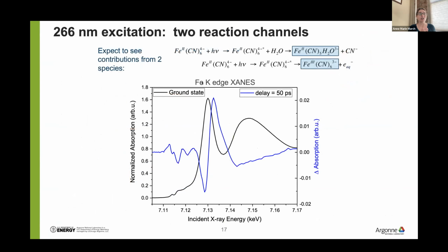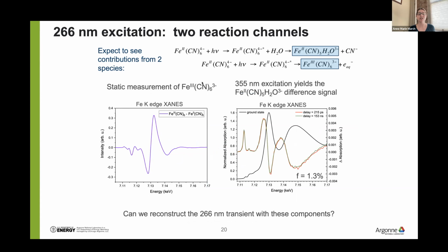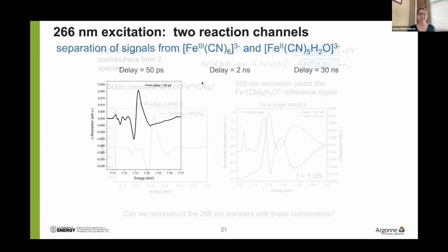We also studied this at 266 nanometer excitation, where we have both reaction channels. Here you expect to see contributions from the 2 products, the aquated product, but also ferricyanide. Here we have 50 picosecond delay, 2 nanosecond delay, and 30 nanosecond delay. You can see that the shape of the difference spectrum is changing here, as opposed to the aquation situation. So we said, okay, can we reconstruct these different spectra using what we know for the shape of the ferricyanide spectrum, which we can measure statically, and what we just measured for the aquated spectrum? We can take these 2 pieces and reconstruct. And the answer is yes.